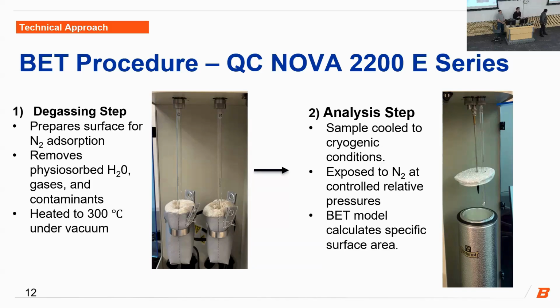We then move it over to the analysis step, where the sample is cooled to cryogenic conditions in the liquid nitrogen dewar. It's then exposed to gas nitrogen at controlled relative pressures, and the BET model calculates the surface area automatically from there.